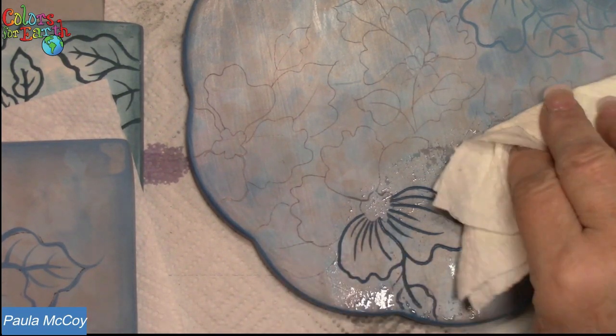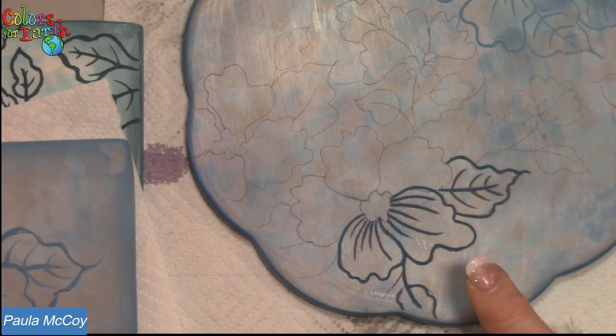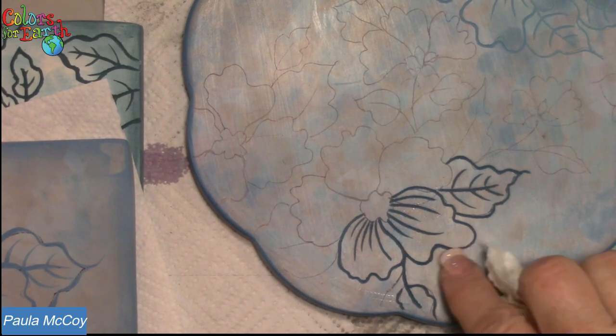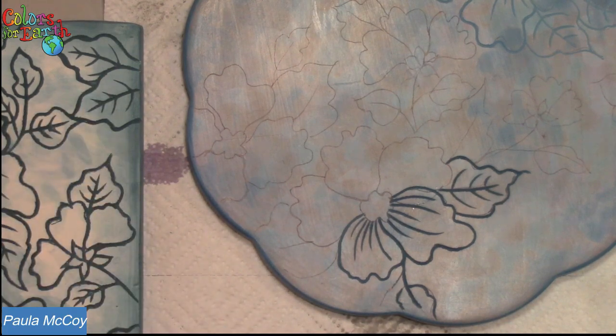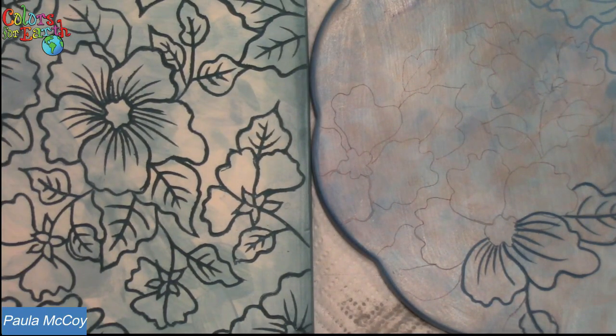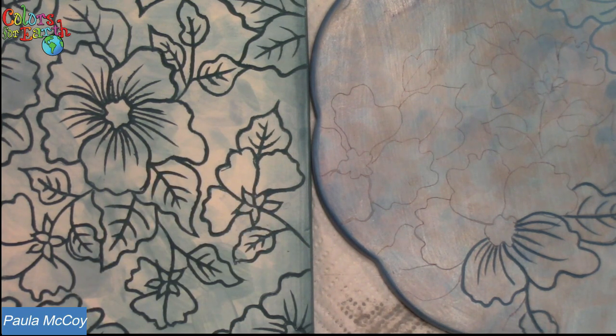Now take a paper towel and wipe off the excess, because when that wax burns away, whatever color is on it is going to roll or bead up. And you don't want that to fall on your piece somewhere else. And then these are the same colors that I used here and I used here. So unfired, this is the greenware. This is the bisque that's been fired to 04. Now I can come back and I can clear glaze.